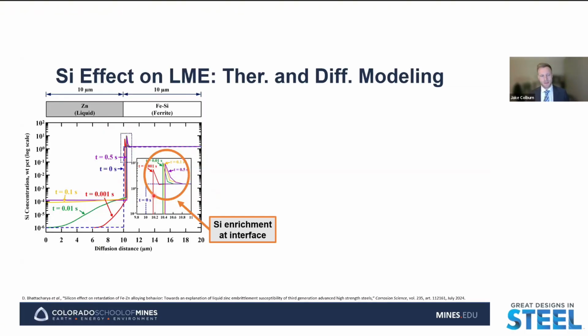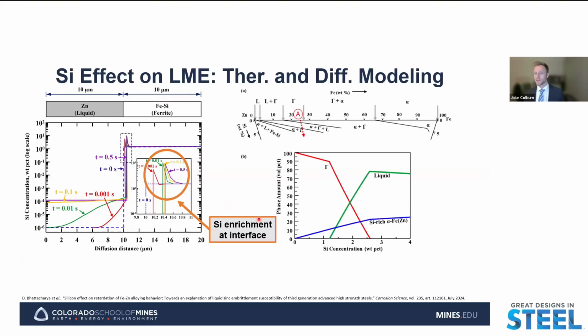And so as the liquid zinc dissolves the substrate, the silicon has very low solubility in the liquid phase as compared to the iron in the steel. And so the iron is able to be dissolved into the liquid, whereas the silicon will accumulate or enrich at the interface as that interface is moving in towards the substrate. And so if we're having a change in the local composition at the interface, if we're increasing the content of silicon at the interface, we'd expect that that can potentially affect what phases are stable, what phases can form, and the fractions of those phases at the interface.